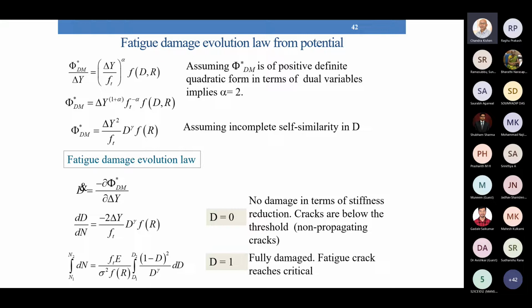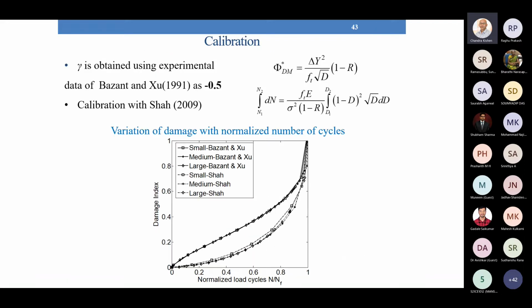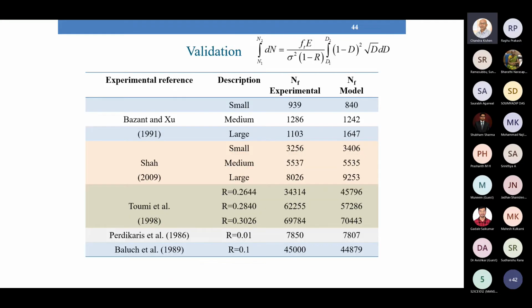Here we consider a representative volume element and we propagate the crack step by step. And we can determine the number of cycles taken for the crack to propagate in each step. That is, in each step we assume that the damage initially is 0, and once it reaches 1, we determine the number of cycles and carry out the analysis. So these are some of the validations, and we see that the experimentally obtained failure cycles are in close agreement with what we obtained from the model.